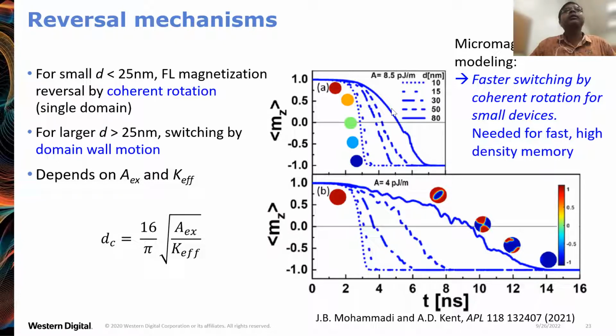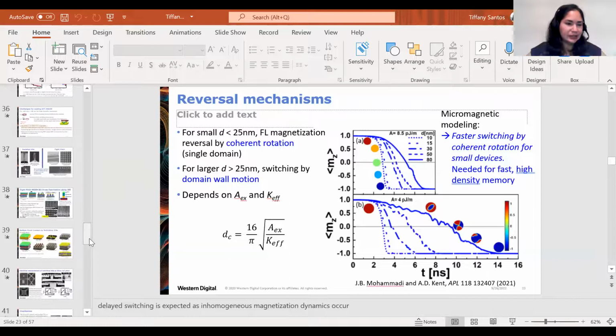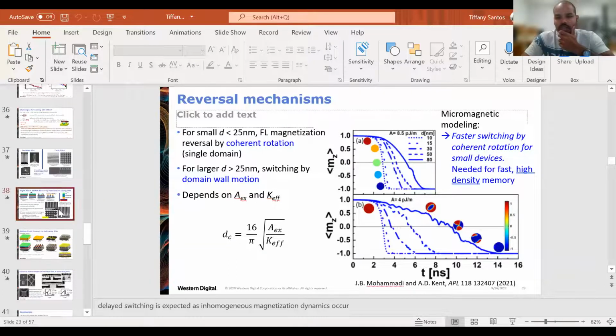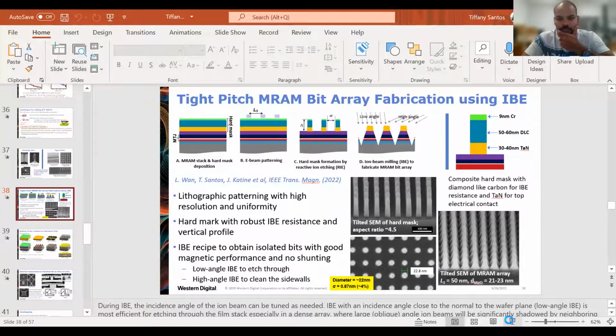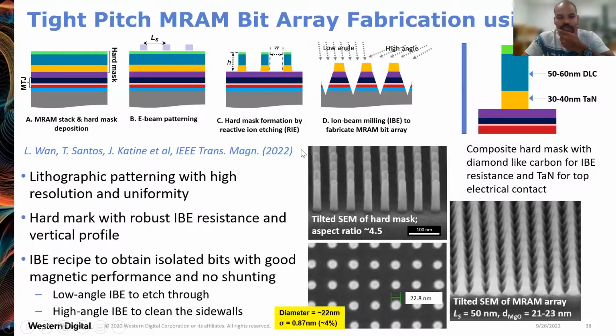Hi, Tiffany. I also have one question. Okay, continue on. Yeah, hi. It was regarding the redeposition of the edges. I mean, after we do the ion milling, there will be redeposition that leads to shorting of the MTJ. So in this case, you use a 3-layer hard mask in order to avoid that issue. But my point is, because I am also facing this current issue of getting shorting of the layer, how can we remove this 3-layer mask without leaving any impurities on the sample itself?